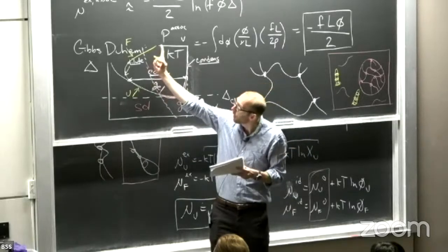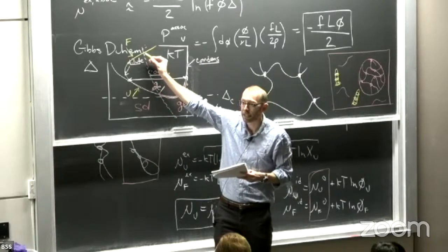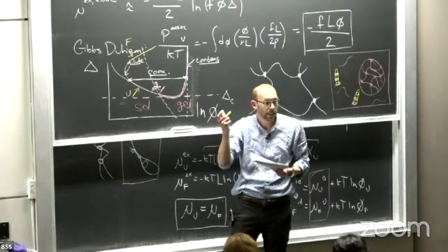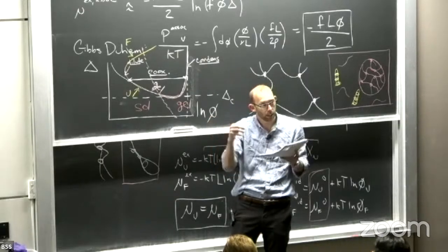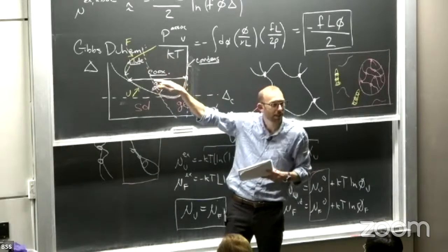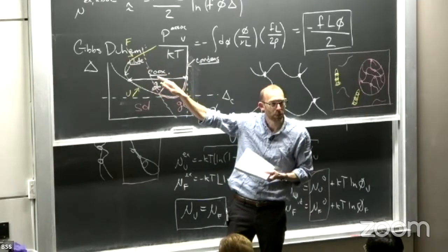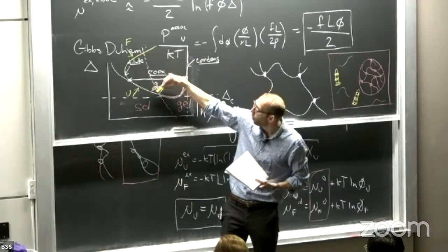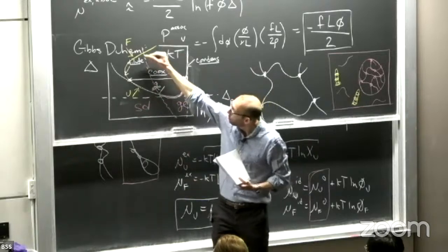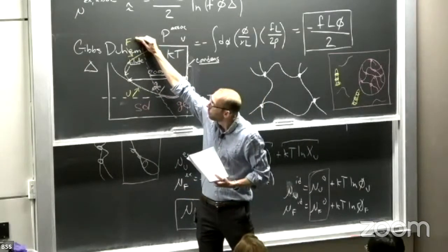If you go all the way in this direction, you'll eventually have roughly the same number of bonds formed in both phases, and it really comes down to the details of the conformational entropy involved in the polymer, which goes beyond these simple arguments we're making here. But overall, you can get a dilute phase boundary that turns around, which means that you can get reentrant phase transitions.